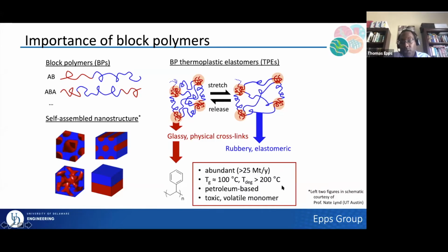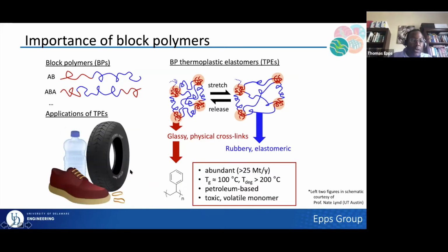Now, when we think about degradation temperature greater than 200 degrees, why is that important? Because in many cases, if we want to melt process our material, we want to have a good window, in this case 100 degrees, between that glass transition temperature where it becomes soft and has more of an ability to flow, and that degradation temperature above which I can no longer process that material. Now, two advantages that we hopefully have with these bio-based materials is we're not petroleum-based, and our monomer, as opposed to styrene, is not going to be toxic or volatile. And again, as I mentioned, just some of the applications, so shoe soles, car tires, rubber bands, and even different types of packaging, etc.